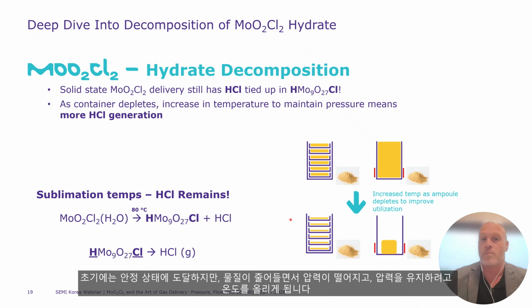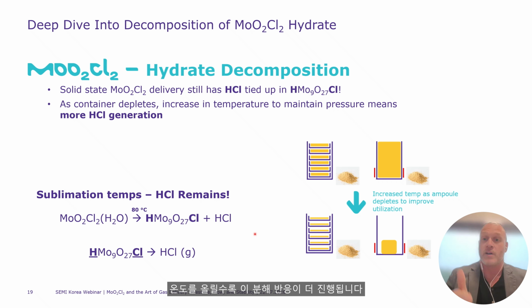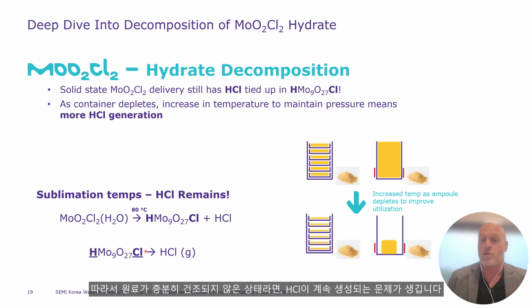So you basically reach a steady state at the beginning. You start to deplete, your pressure drops, and as the pressure drops, you increase temperature. As you increase temperature, you start driving this reaction forward. So you start decomposing this molecule into HCl. And so you have an HCl source if you don't have appropriately dried starting material.